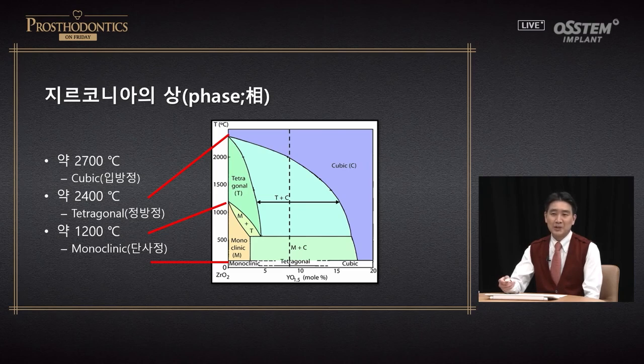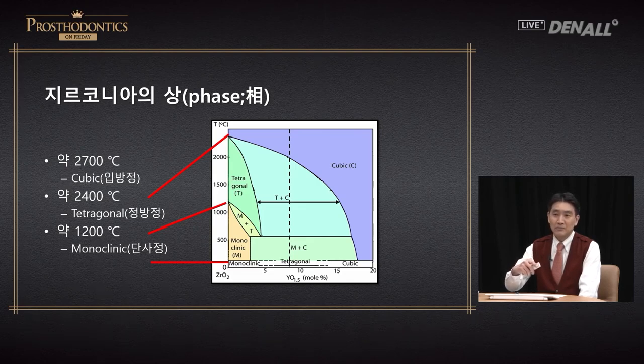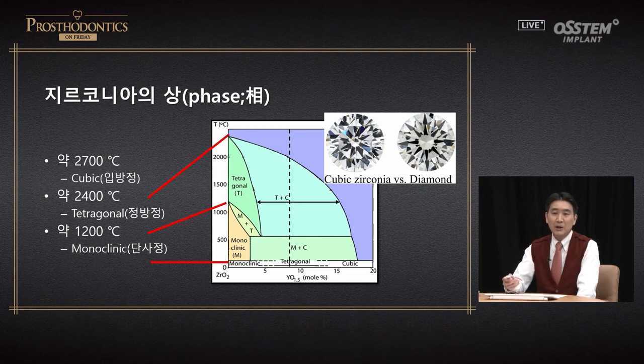Let's look deeper into zirconia. It doesn't look interesting, but we need to study. Zirconia's melting point is 2,700 Celsius. From room temperature it is in the monoclinic phase, then the tetragonal phase above 1200 Celsius. And if it exceeds 2400 Celsius, it has a cubic phase. If you use stabilizers like yttria or magnesia, it does not return to monoclinic. It maintains the phase, say cubic phase or tetragonal phase, even when the temperature drops. I'm sure you know of cubic zirconia, and this is zirconia which has been stabilized in cubic phase. And that's how you make a cubic zirconia or artificial diamond.